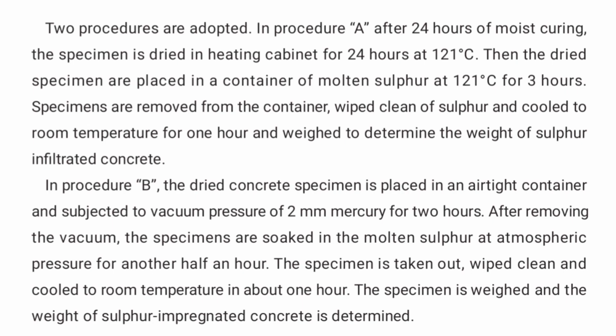In procedure B, the dried concrete specimen is placed in an airtight container and subjected to vacuum pressure of 2 mm mercury for 2 hours. After removing the vacuum, the specimens are soaked in the molten sulphur at atmospheric pressure for another half an hour. The specimen is taken out, wiped clean and cooled to room temperature in about 1 hour. The specimen is weighed and the weight of sulphur impregnated concrete is determined.